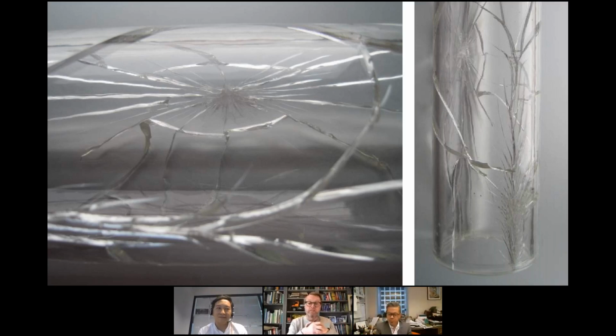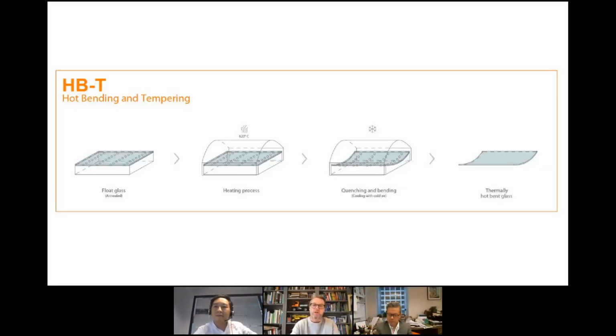And we didn't quite get to the point where we were satisfied that making 308 tubes in this manner was not going to yield a significant number of failures in the fabrication. So it was relatively quickly written off as something that we unfortunately couldn't use for this particular application. So we moved on and we were looking at hot bending and tempering.